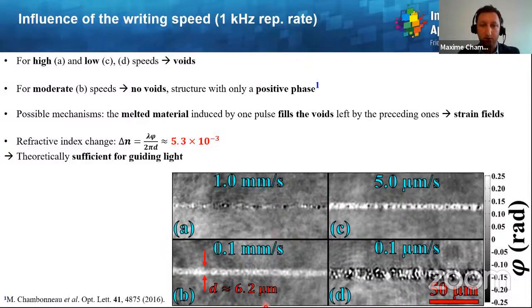In stark contrast, when the writing speed is intermediate at 0.1 millimeter per second, one can see that there is no black dot in the line, and we have inscribed the structures as lines with a positive phase shift, meaning that there is a positive refractive index change.